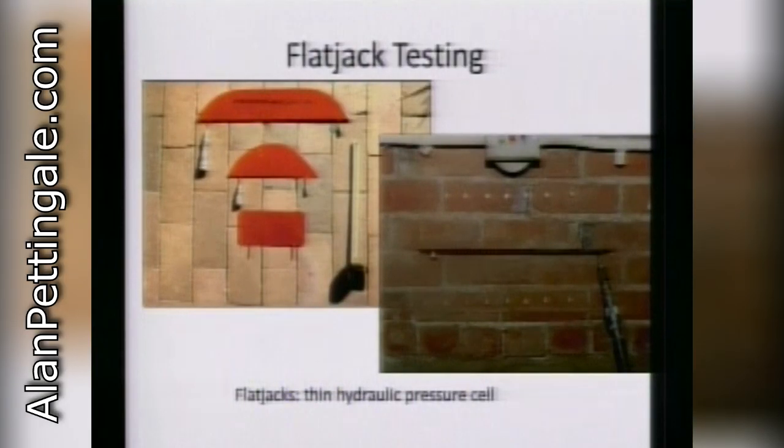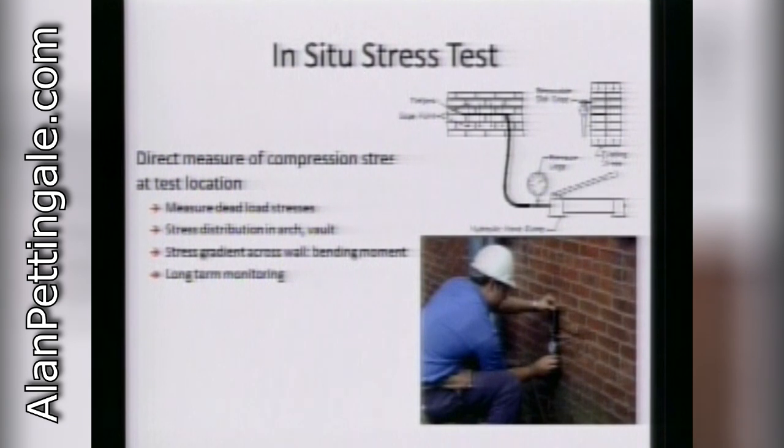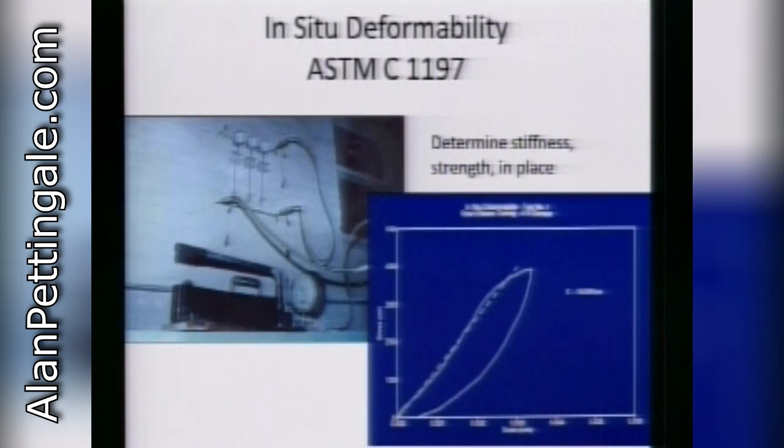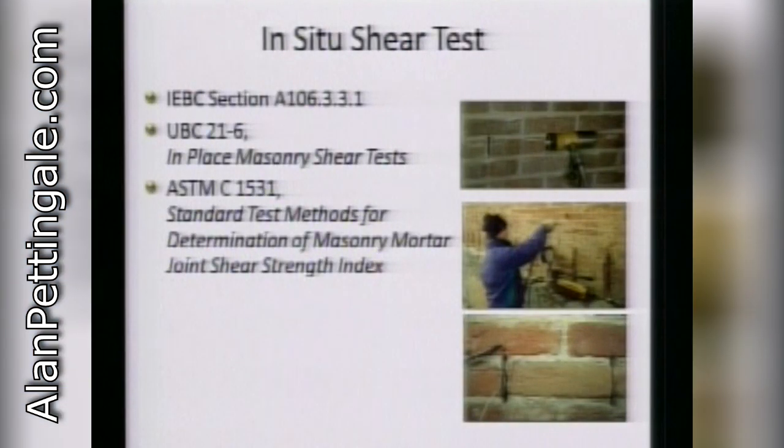With just one flat jack, you can determine the in situ stresses, which is valuable if you want to understand what is actually holding up the wall. Pictures of the equipment show it in use, and from the tests you can determine in situ deformability, stiffness, strength in place, and get hysteresis curves. In situ shear tests are also possible.